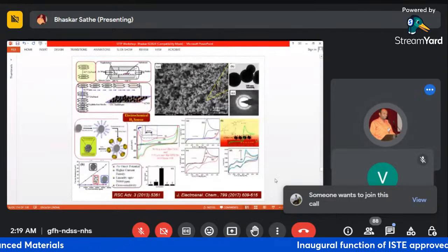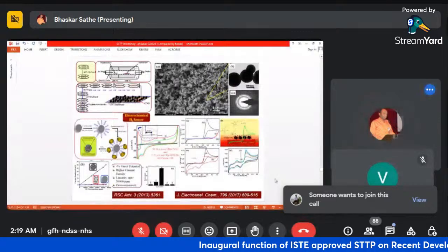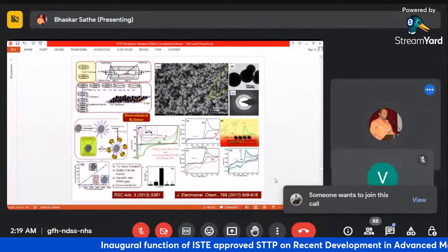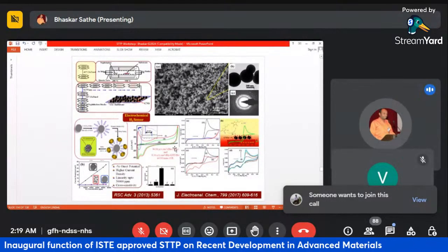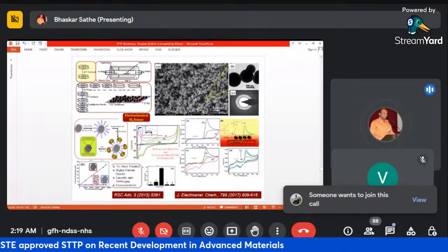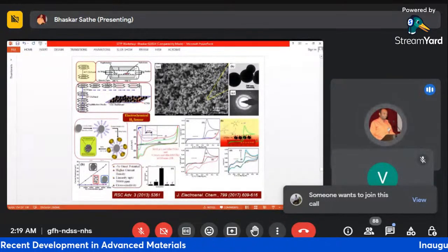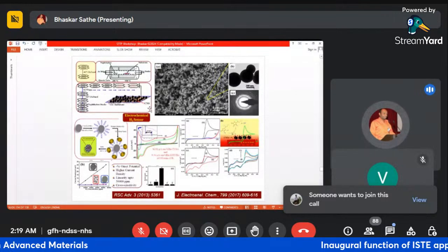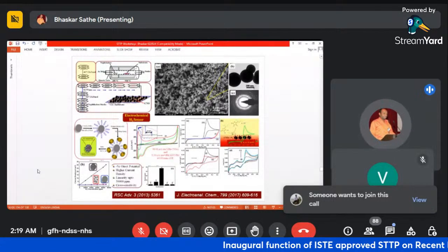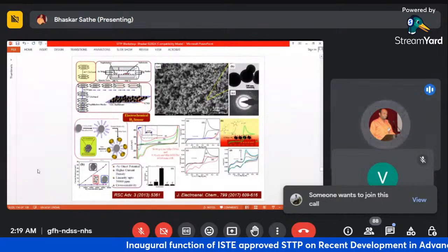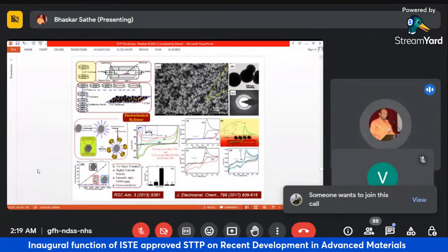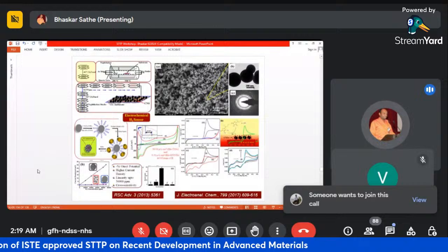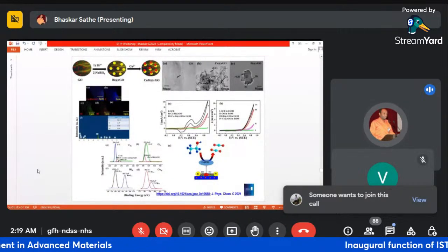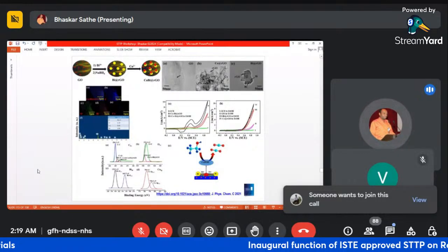In another case, we have developed nanospheres of carbon by using a mixture of naphthalene and camphor together. This system is good as a metal free system for ascorbic acid oxidation as one of the fuel cell reactions. Right. Some other fuel cell reactions we have also done on the bismuth cobalt cluster, which is decorated on the graphene, and this system is good for ethanol oxidation.